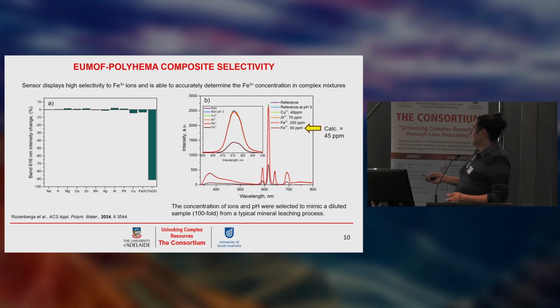And if you calculate the concentration of the ferric ions in this mixture, based on that reduction in emission, you get a value of about 45 ppm. And that's extremely close to the original value in solution. So even in this complex mixture, the composite can very accurately detect or determine the concentration of ferric ions in solution.